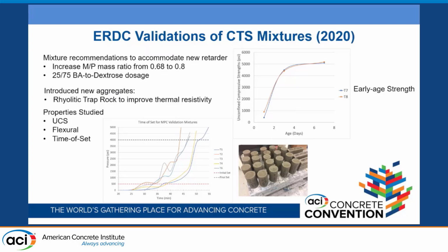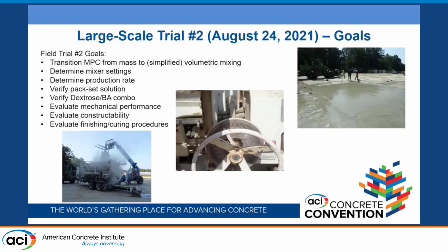So the properties studied: unconfined compressive strength, flexural strength, and time of set, and time of set is interesting. As you can see, we eventually got to about 40 minutes for the initial set, and then it really takes off after there. And I have some more research I'd like to do about time of set with that thixotropic behavior I was talking about.